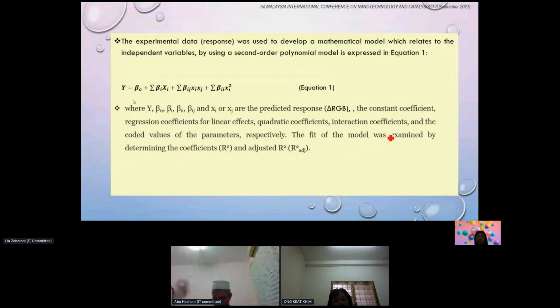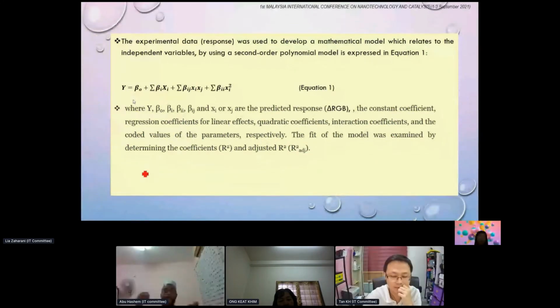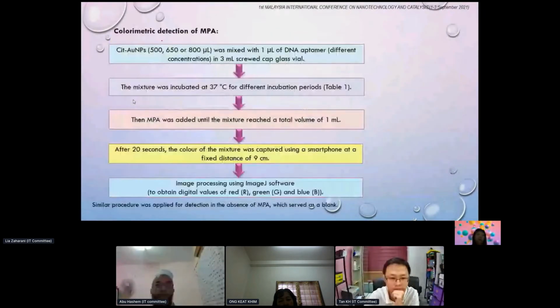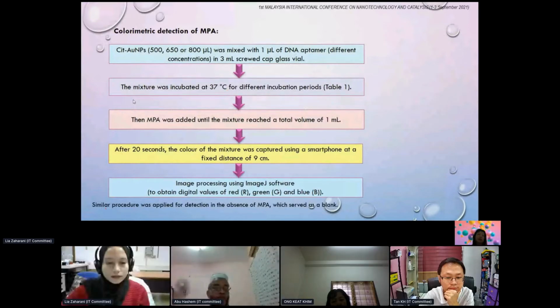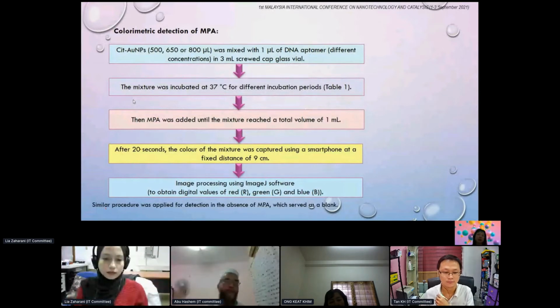The fit of the model was examined by determining the coefficient and adjusted R squared. This slide shows colorimetric detection of MPA. Cit-AuNPs was mixed with 1 microliter of DNA aptamer in a 3 milliliter cap glass vial. The mixture was incubated at 37 degrees Celsius for different incubation periods. The MPA was added until the mixture reached a total volume of 1 ml.